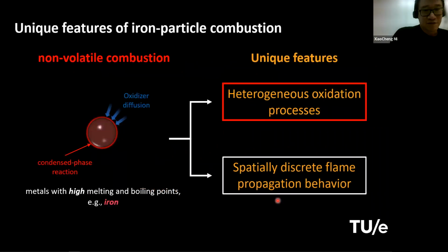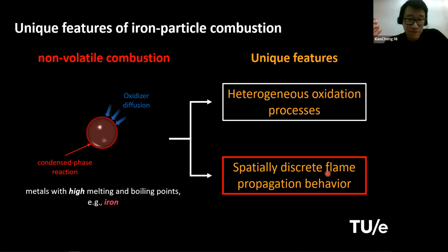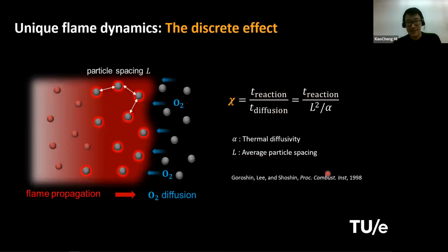Okay, I will go relatively fast with the other feature because it is even more complex and we have even less certain answer to it, but I think it's still very interesting. As I said, since iron particle has very non-volatile combustion, the energy release is within the very close vicinity of the particle, and this will make the overall energy release over space highly non-uniform or highly discrete. So to understand this phenomena, we can look at this ratio between two key timescales. One is the reaction time. T reaction is the time over which an iron particle releases its energy, and the other is the characteristic time scale for the heat to diffuse from one particle to its neighbor, right?